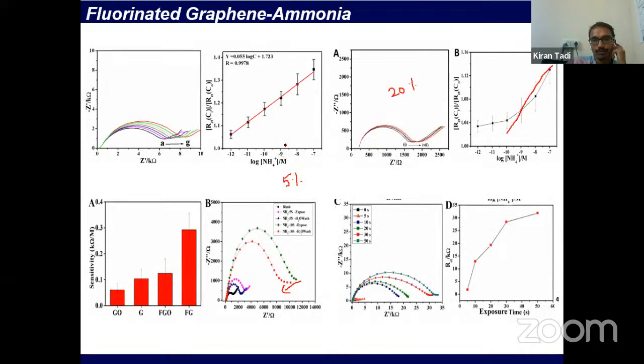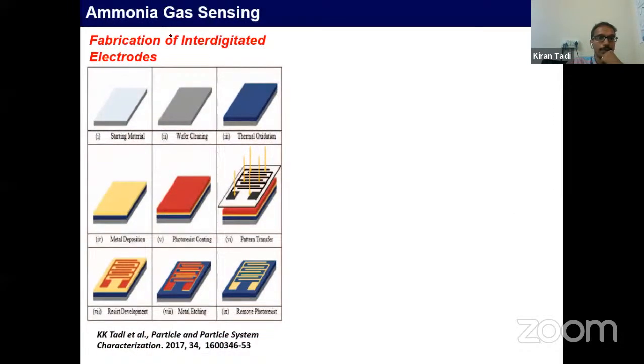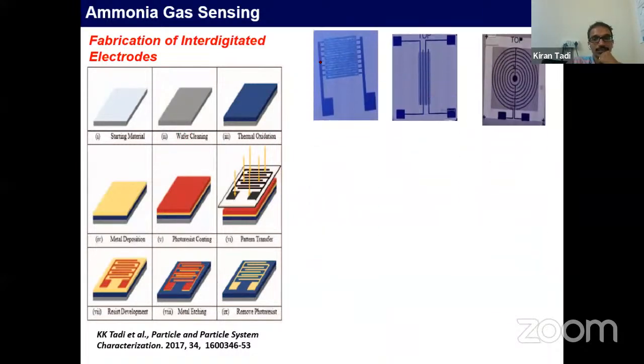Once we got a successful result with this multi-layered graphene, we synthesized the CVD-based graphene, which is a single layer, and fabricated chips with interdigitated electrodes under clean room conditions. These specifications are around 1.5 centimeters by 1.5 centimeters chips with interdigitated electrodes. On that, we deposited a single layer of graphene using the CVD method, chemical vapor deposition.